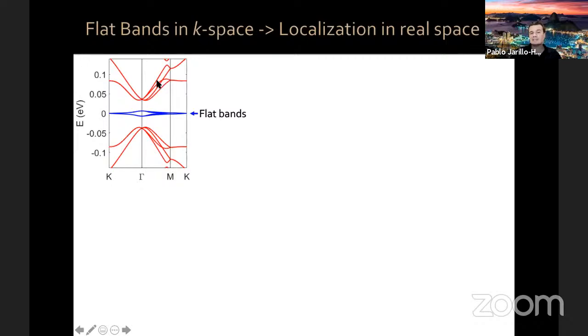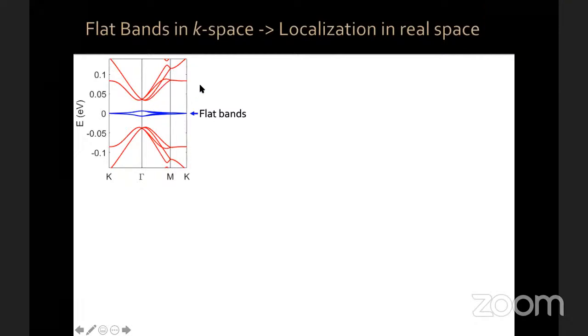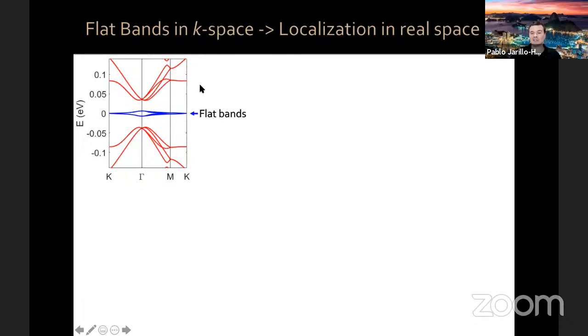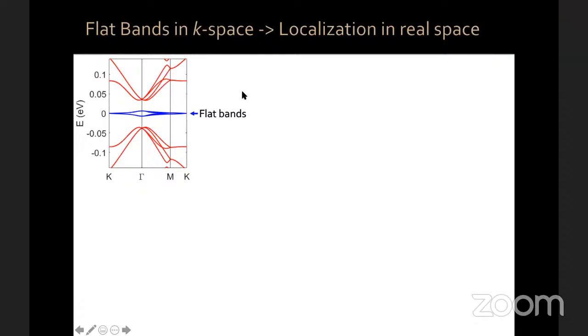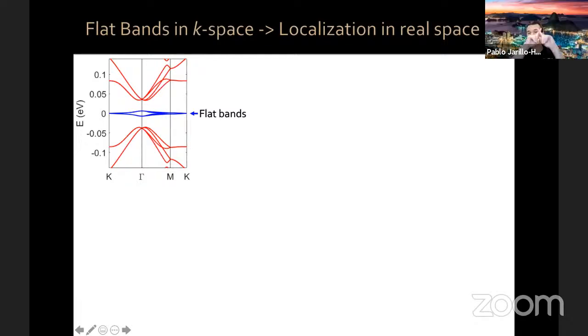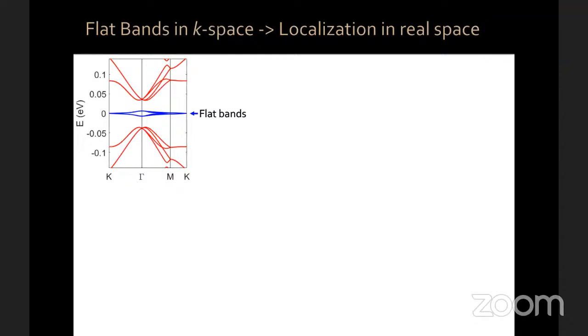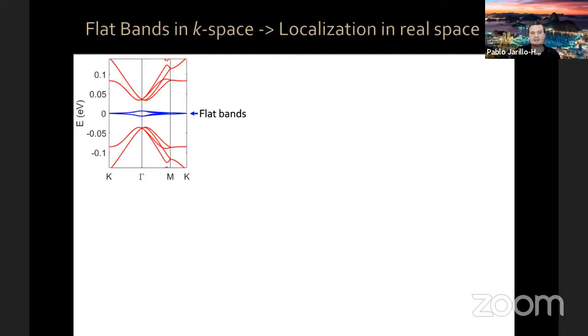Okay, I have to say that this calculation is a simplified model where indeed you see that there is symmetry. If you do a more realistic calculation, there is actually substantial asymmetry already at the single particle level. As you may know, graphene seems quite symmetric at low energies, but if you go to high energies, there is actually substantial asymmetry in the electronic structure of graphene. All that high energy asymmetry gets folded down to low energies when you do this Moiré superlattice. I see. Once you start incorporating the actual electronic structure, this is not an accurate picture. It's asymmetric.